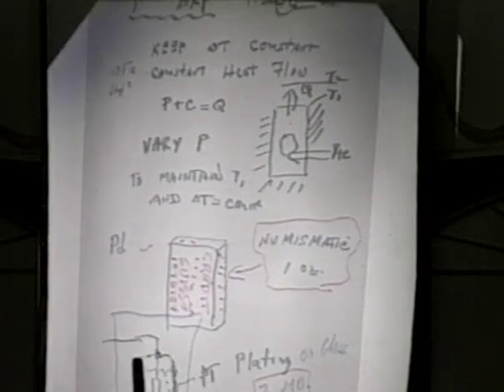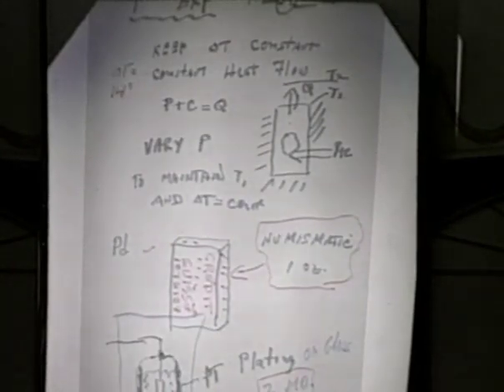We plated platinum throughout the inside of the glass enclosure and had an electrode going through the glass to contact the platinum, and spot welded a platinum lead to the bar over here and covered the whole thing with the lithium hydroxide solution that we made. And we ran this thing for 2 months.